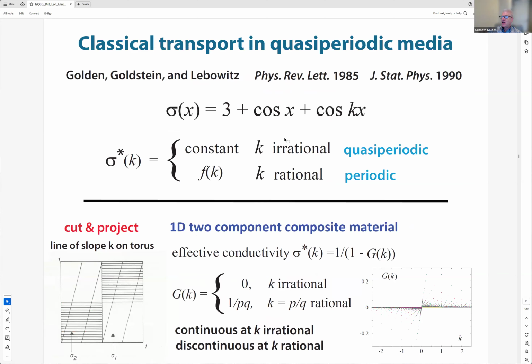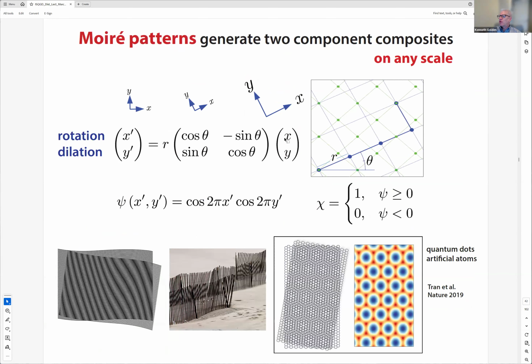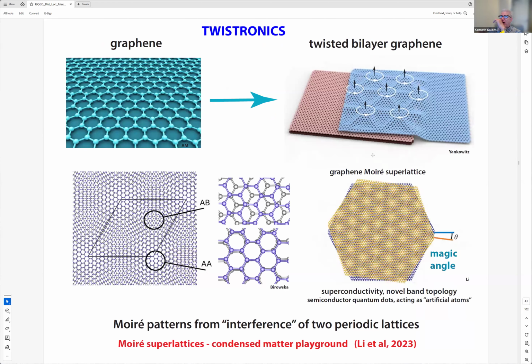But then David had a much better idea where he looked at moire patterns. In other words, take a mathematical lattice and twist them relative to each other, twist and expand. So you have a parameter space of R, the expansion parameter, and the twist angle. And then that provides a template to lay down two different materials. This is very similar to these driftwood fences where you see moire patterns. But then this gets into quantum dots, artificial atoms, all this really fascinating stuff that's been going on in condensed matter physics in the last 10, 15 years, in particular twistronics. Namely, there's graphene, and you can take two layers of graphene and twist them relative to each other, get superconducting states, all kinds of fascinating behavior.